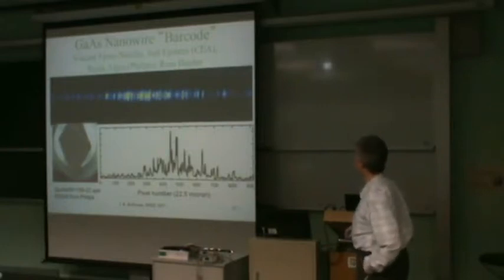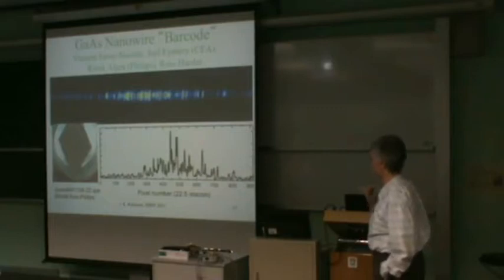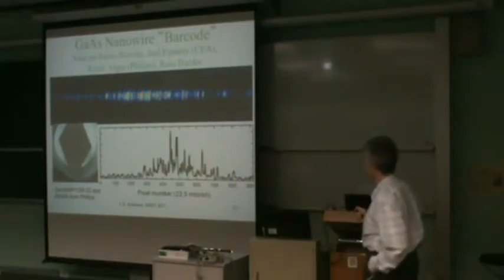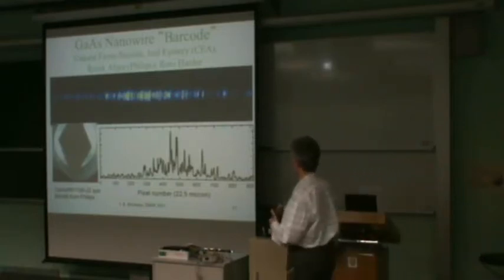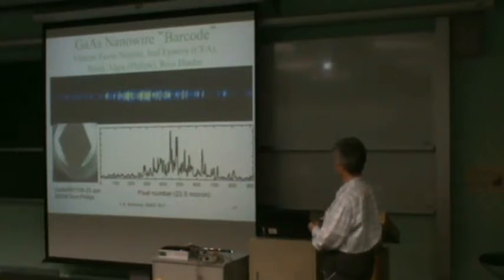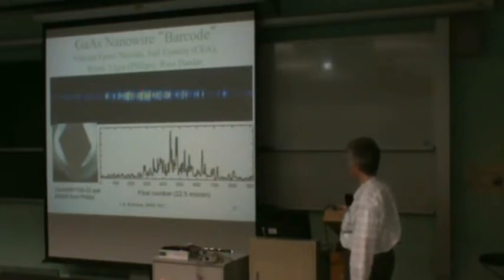In fact, stacking faults are the next thing I wanted to talk about. These are gallium arsenide wires that are measured. And here, this is just showing the raw diffraction pattern of one of these wires. The little elliptical streak here is the Fourier transform of the cross-section of the wire itself. So the width of the wire is shown as the reciprocal of the extent of this diffraction pattern here. And what's very interesting is that there's a pseudo-random sequence of peaks which comes from the length of the wire that is being illuminated, and when we move the beam along the wire, we get a different distribution of these peaks. And we've been trying to develop a method to invert this so-called barcode pattern into an image, and the closest we've got is this work by Vincent, which is shown here.